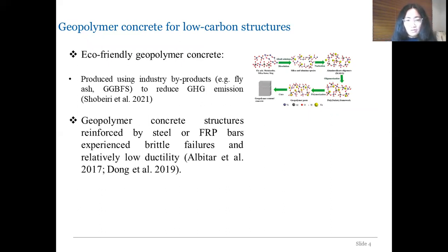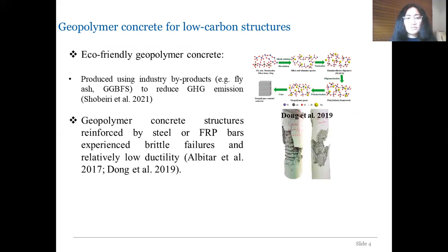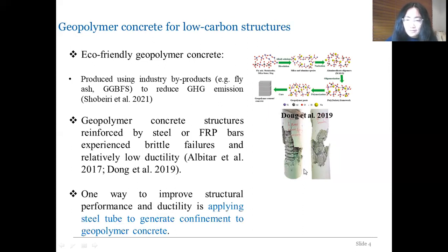But in order to use geopolymer concrete to form structures for our infrastructures, we need to examine the structural performance. But existing studies mainly focus on the geopolymer concrete structures reinforced by steel or FRP bars. And the research shows that these structures experience brittle failures and very low ductility, especially for the columns. The ultimate loss of the resistance reduced all of a sudden, once the peak load was reached, and the load dropped by 90% or even 100% due to the brittleness, the brittle failure of the structure, as shown on the right-hand side of the spalling of the geopolymer concrete.